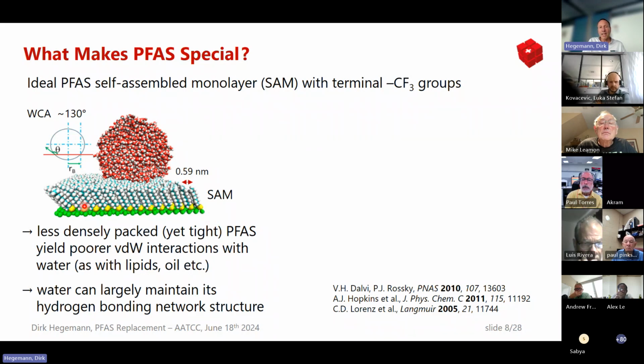You can do some studies with an ideal self-assembled monolayer, where you only have chains of CF2 groups and terminal CF3 groups. They indeed have quite some space among each other, even when they are tightly packed on a surface. That adds to the effect of a very low interacting surface area, and that repels not only water, but all other liquids and stains as well, since they can retain their shape and are repelled. That would be the ideal situation, which tells you a few nanometers should be sufficient to reach these extremely good effects.